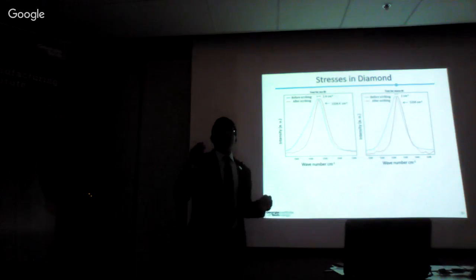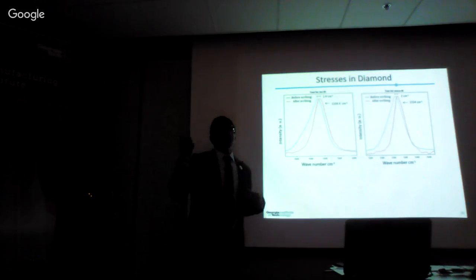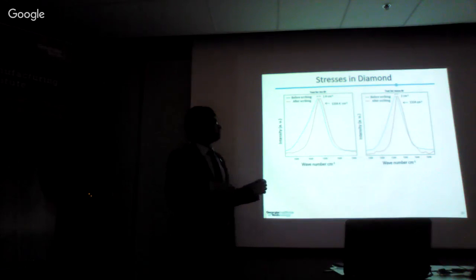And I talked about doing Raman analysis to find the stresses in diamond. So diamond as a material has a Raman spectrum with a peak at 1332 centimeter inverse, which is the pristine diamond peak. Diamond can phase transform into graphite and other phases, but for that it requires very high stresses and temperature. We did not find that in our experiments, even though some others have found limited graphitization in the diamond wire sawing process. What we found is that both the tools showed a peak, the blue one, before scribing at 1332 centimeter inverse.